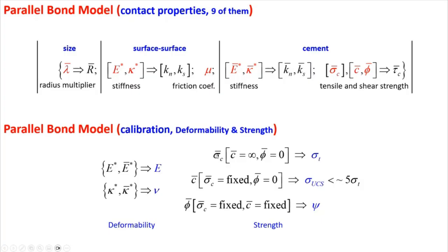Then we're going to do a UCS test to measure the UCS. We'll just take this exact thing with the value we have, run the UCS test, and now we're going to have a free parameter, which is going to be that cohesion. And the cohesion controls the shear strength. Remember, we started with the material unable to fail in shear. But we have to let it, because rock is going to have some failure, typically near the peak. In a UCS test, you start to get some micro shear failure. And that micro shear failure allows the entire specimen to form a coherent fracture or shear band so that it actually fails. So now, instead of having it be infinity, we make it smaller and smaller. Eventually, we're going to get some shear failure.